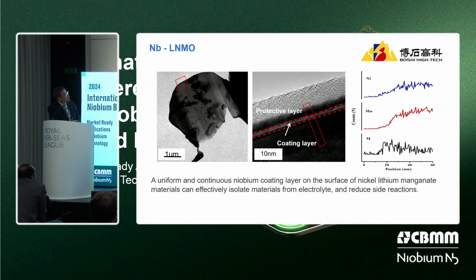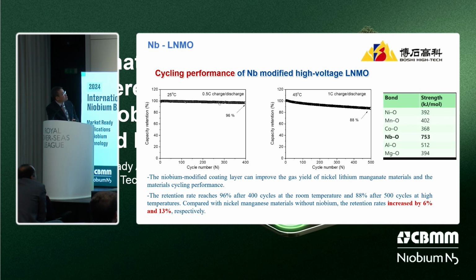And this is the data from Boshi for LNMO. They developed a very thin lithium niobate coating layer. And for the performance, this is the cycling performance of niobium modified. This is at room temperature and at a higher temperature, 45 degrees. Both of these are niobium modified. And compared with without niobium modified, this one increased 6%. And this one increased 13% respectively.